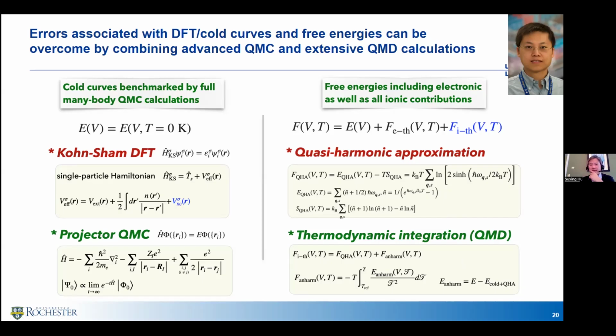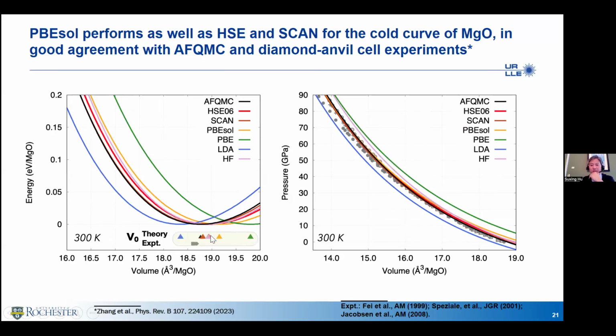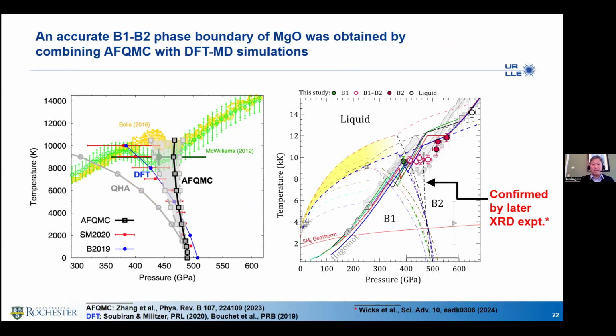So by combining these techniques, he can figure out that the SCAN functional and also this hybrid HSE functional can give you the best results, in good agreement with the QMC calculation. And PBEsol, that's like a GGA exchange correlation functional, gives you good results. Remember, SCAN is also, as I just showed you from Katie's work, giving good results for the SiO2 system. So then Sui used the best identified functionals, did the QMD calculation, combined this together, and he can figure out this phase transition boundary.